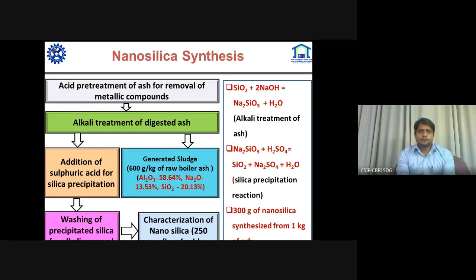Synthesis and characterization of nanosilica. Nanosilica synthesis was performed with boiler ash. The acid pretreatment of ash for the removal of metallic compounds from the ash was performed. Then the alkali treatment of digested ash was performed. Then sulfuric acid was added for silica precipitation. As you can see in the reactions, silicon oxide was reacted with sodium hydroxide, which converted to sodium silicate and H2O, and this sodium silicate will react with sulfuric acid, which will produce silica, sodium sulfate and H2O.